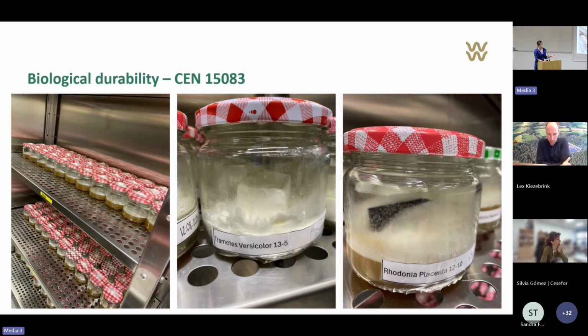Once again we ran the durability test, and after improving the curing and impregnation process, against white rot we achieved durability class 1, which was a big surprise and a really nice step. With the brown rot, our test failed - it didn't pass the results required for validity against the reference sample. So we're repeating some of them, and we still have them in progress.